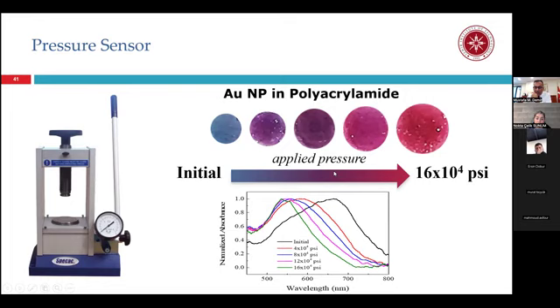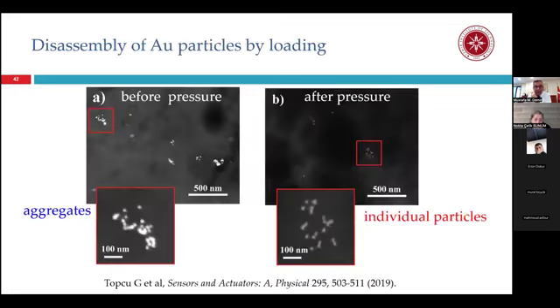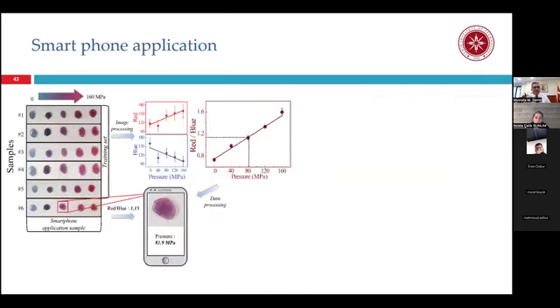As you see in the spectrum, we have seen all colors in the spectrum in the material upon application of mechanical stress. So these are electron microscope images before and after application of pressure. Before application, you see large aggregates. The particles are close to each other. We see coupling of plasmons. Then after application of pressure, you see the particles are separated from each other, and we see surface plasmon, and we see the red color of the gold nanoparticles.